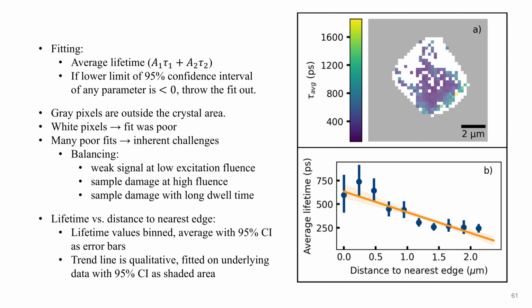I did this fitting, and just to get a quick view, I did an average lifetime where I took the amplitude and weighted the lifetimes with the amplitude. And then I got the error out of the fitting for all the parameters and propagated that error to the average. And I said, okay, if the 95% confidence interval, the lower limit of that interval is less than or equal to 0, throw it out. So I didn't want to take anything where the fit was not good.